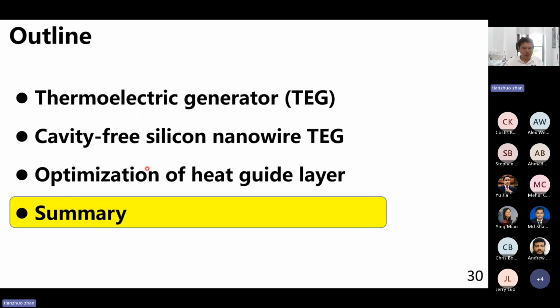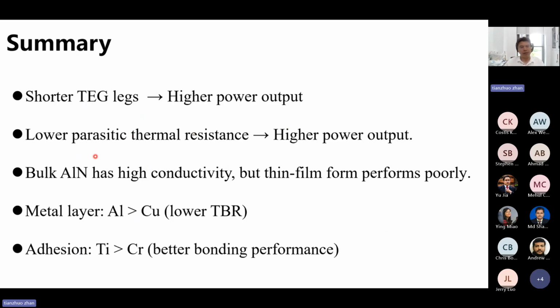And so finally, I will summarize the results. We found that the power density can be improved by shortening the TEG legs, and also by lowering parasitic thermal resistance. And for the heat spreader layer, even though aluminum nitride has a high thermal conductivity, the thin film form performs very poorly. And also for the metal-dielectric heat spreader layers, we found that aluminum is better than copper due to its lower TBR, and titanium is better than chromium due to its better bonding performance between different layers, resulting in a lower TBR.